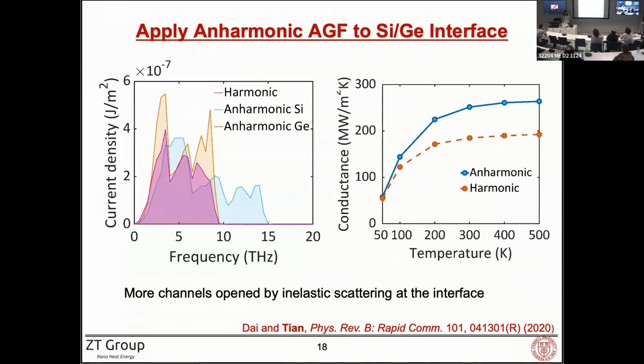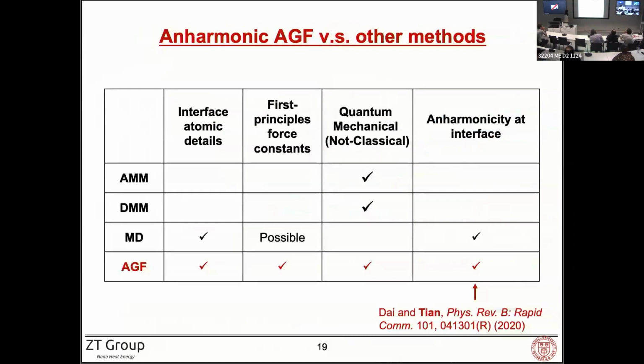But with the inelastic scattering, where we allow three-phonon scattering to happen at the interface, we can access some of the phonons where the density of states don't overlap between silicon and germanium, because inelastic scattering opens up extra channels at the interface. And that leads to enhanced thermal interface conductance compared to the harmonic case. So we are very proud to come back to this table and put a check mark there.